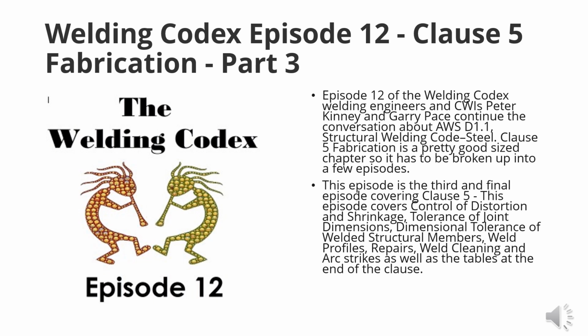Exactly. This is one you're going to have to read a couple of times, and it basically just gives you the number on your offset. So 10% of the thickness of the thinner part joined, or an 1/8 of an inch, whichever is smaller. So you're not going to get a hell of a lot of misalignment allowed here. It's either 10% of that thickness or it's an 1/8 of an inch.